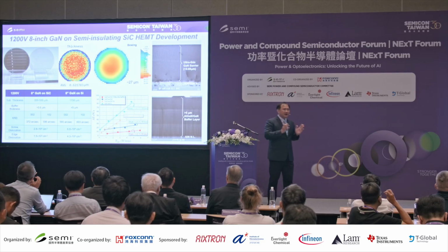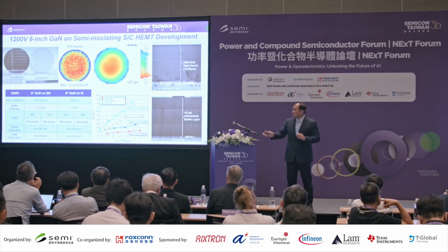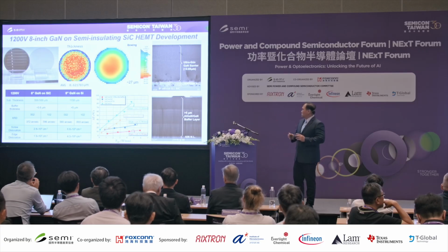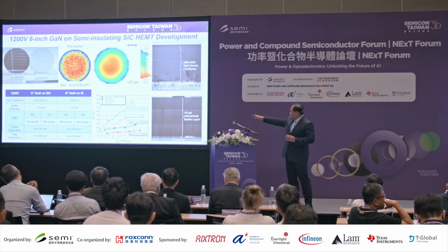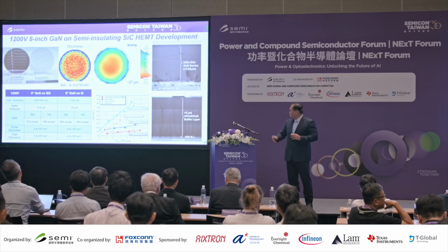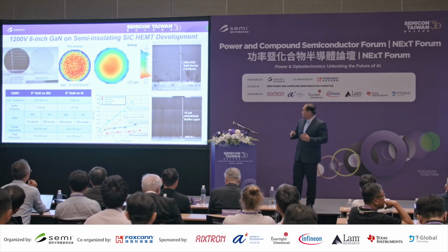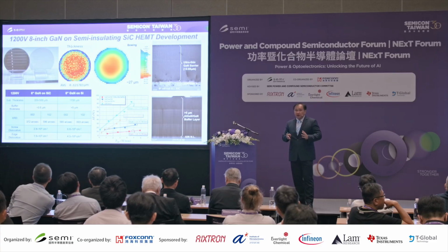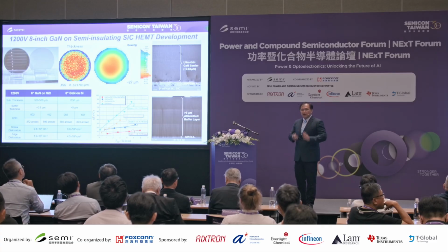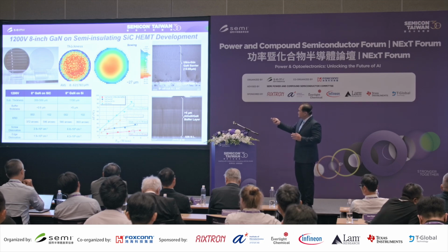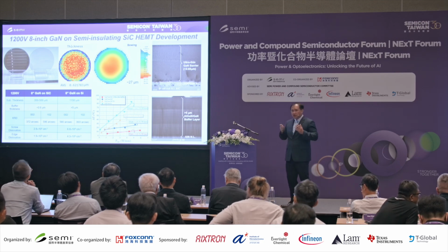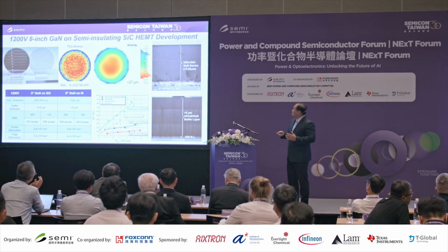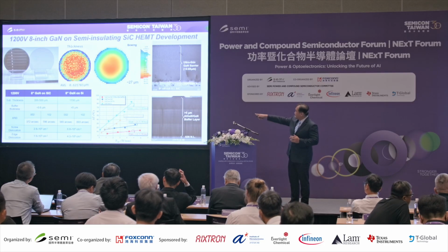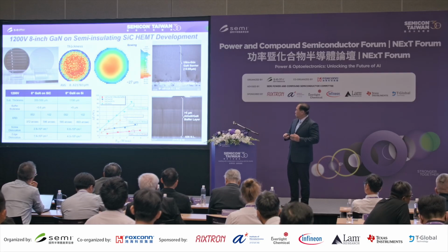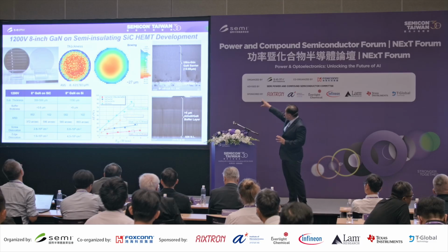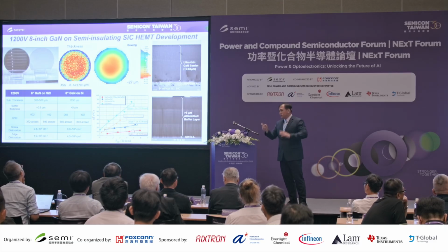If you really put the GaN on silicon for the high power electronics, okay, you have to suffer the very high slope of the PDC to temperature increase. So if you use the GaN on silicon carbide, you have a very, very small slope for the temperature increase, especially the ultra thin buffer. Actually, the less thermal boundary layer. So eventually, we found that the GaN on silicon carbide can get very similar thermal dissipation behavior, just like the silicon carbide vertical device, and with a very good epi quality. It's only 0.65 micron, but the quality is totally different.